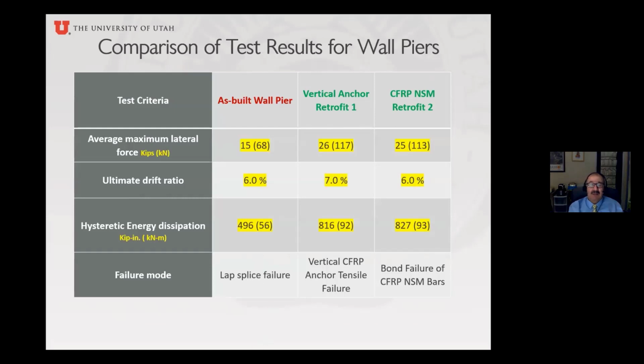So as a summary, for the as-built, the load was 15 kips. Both retrofits achieved 26 kips. The drift ratio for the as-built was 6%. The one with the anchors went to 7%. It was a little better. The near surface was 6%.